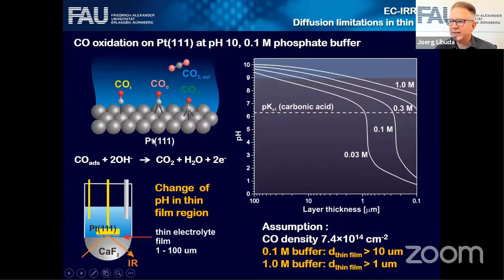So one thing that you have to think about is the geometry that you're using for this experiment. So typically, as I said, there's the single crystal, the window, and that small gap between the single crystal and the window. Yeah, and this small gap typically is in the order of micrometers. Now let's assume that you want to do an electrocatalytic reaction, so for instance, you want to electro-oxidize CO. In such a reaction, you would always generate protons or consume OH. Yeah? So the reaction itself would change the pH, the conditions under which you run the reaction. Now, normally that is no problem because if you're doing electrochemistry, normally you have a buffer. And the buffer makes sure that you're not changing the pH.